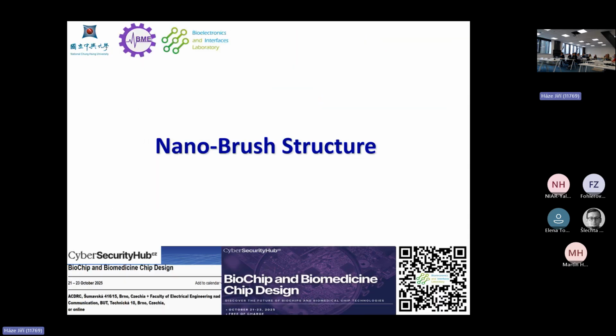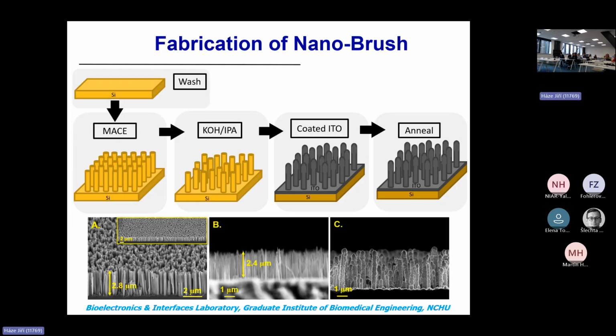And the second part, I'm going to move to the biosensor. The biosensor we used here, we create some nanobrush structure, and we apply this structure to different biosensing applications. So how to fabricate the nanobrush? We use the MACE etching, that is the metal ion assisted chemical etching process. So we prepare the silicon wafer. After washing, use the MACE process, you can get very vertically aligned nanowires.